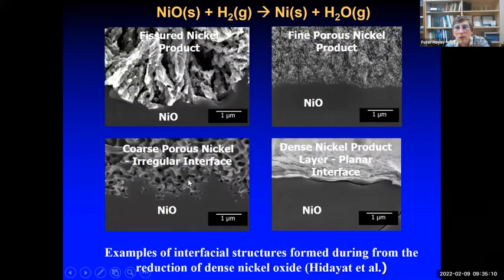So stop, start in here. At the high driving forces and low temperatures, we get this fine porous continuous product where the gas pores go right from the surface of the sample all the way to the nickel oxide interface. So we get gas diffusion all the way there, and the H2O, the reaction product, goes all the way out too. So we have counter diffusion of gases in those fine pores. And at low temperatures, we get a modification of that structure, which I'll explain a bit more about in a minute.